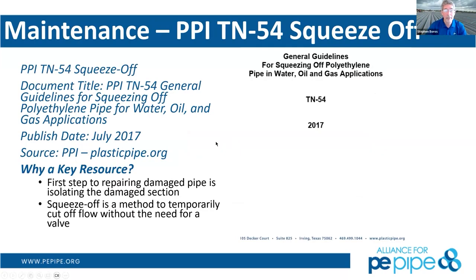Another thing that's unique to polyethylene pipe is squeeze off. People that haven't seen this before don't believe it. But I can guarantee you it is true, it works, and it's a great aspect of polyethylene pipe that can be taken into account. It was actually pioneered by the gas distribution industry into how they can squeeze off polyethylene gas distribution piping to do a tie-in or repair, and then open that pipe back up and the pipe's not damaged. And so you can do that with pipe today up to about 24-inch diameter is about the largest I think they have a squeeze-off tool for.